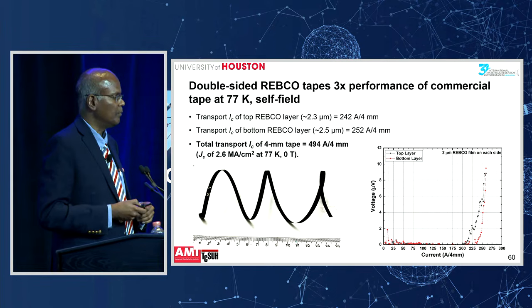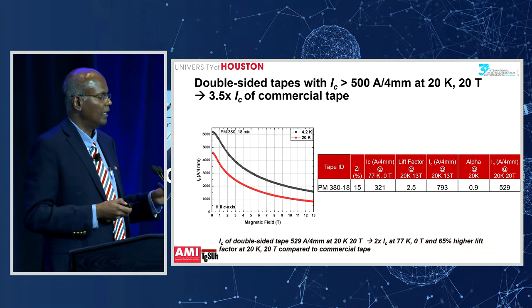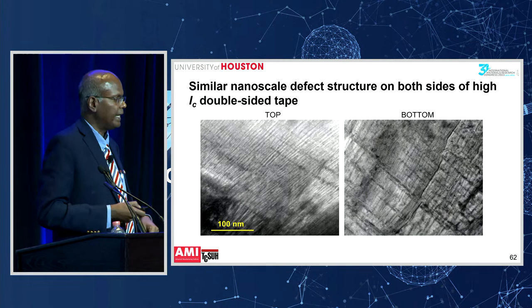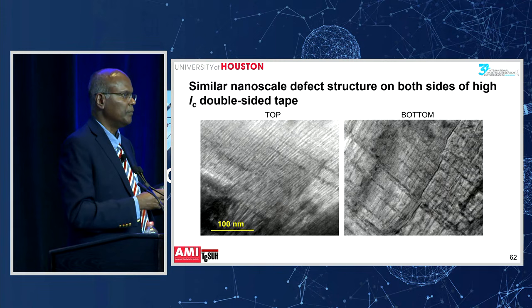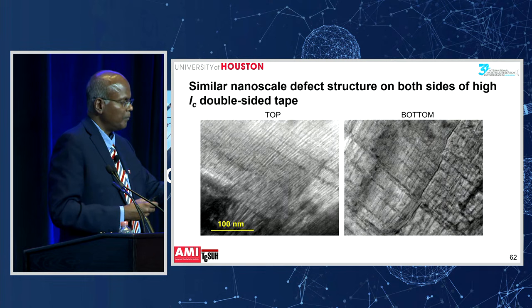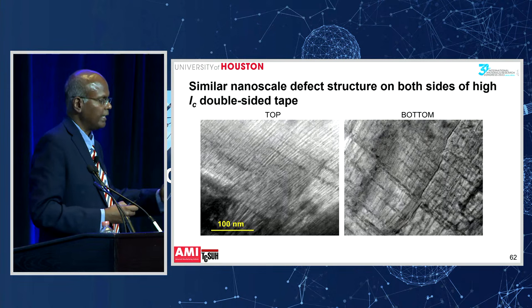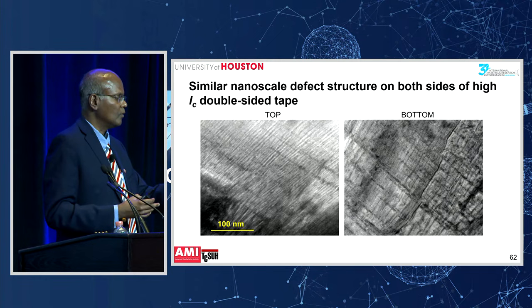And right now, I can skip that because I had a different result. So you can see the barium zirconate nanocolumns on the top side and the bottom side. So both sides were able to implement the self-assembly process. The image is done in an inclined orientation, but the C-axis is actually pointing along the direction of the barium zirconate nanocolumns. So on top and bottom side, you're getting good microstructure of the films, both good epitaxy and good self-assembly of the barium zirconate nanocolumns.